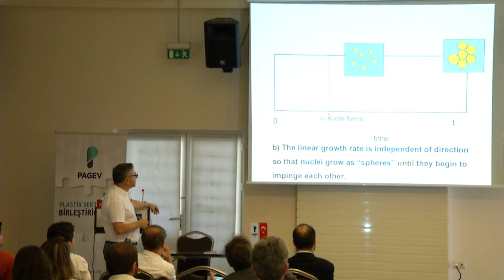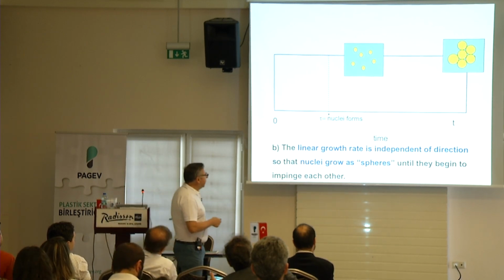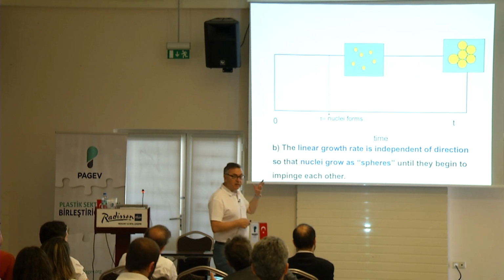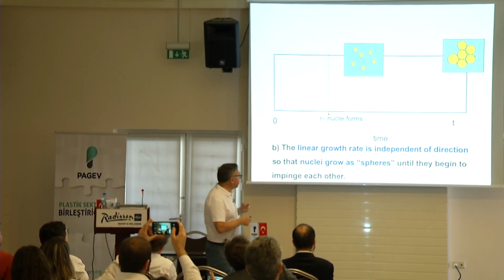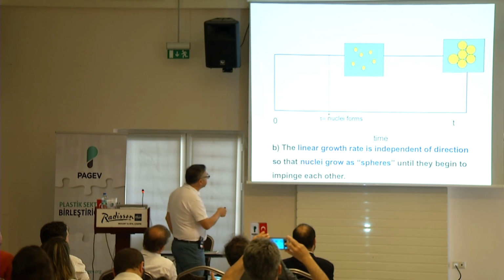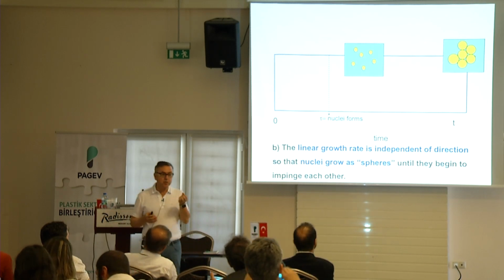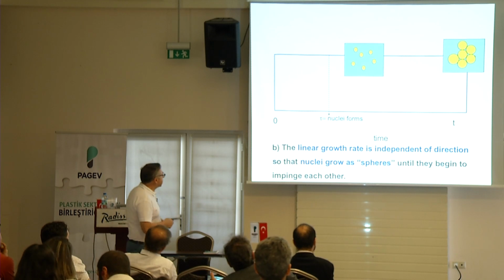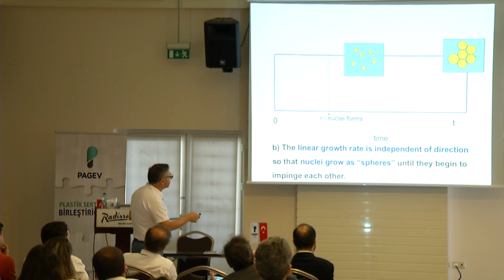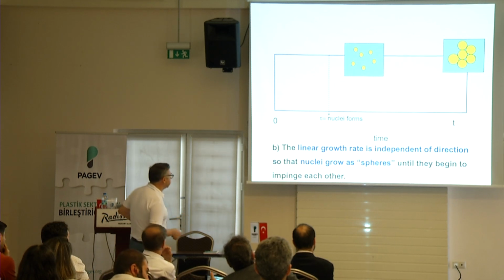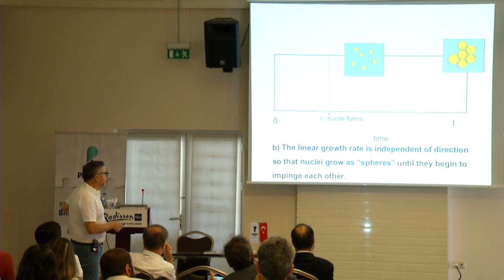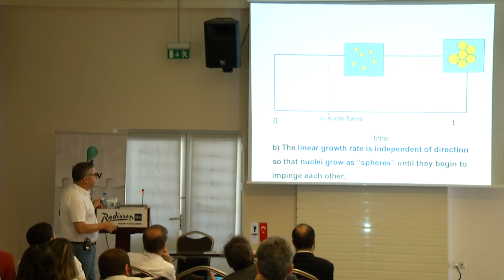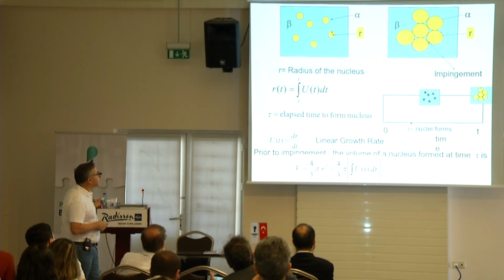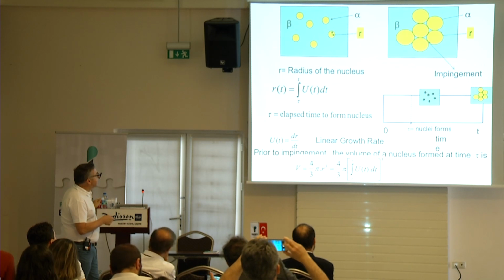So typically what happens is that if you're watching on the microscope, these crystals become visible, as you saw in the video. At some point you start seeing them, but in fact, they form much earlier. You can't see them in an optical microscope. They're just too small, right? And then at time equals 0, the nuclei form, they are independent of each other, and they eventually impinge on each other. And typically linear growth, that's one of the assumptions that they typically use, linear growth rate. When it's a linear growth rate, that's relatively simple.